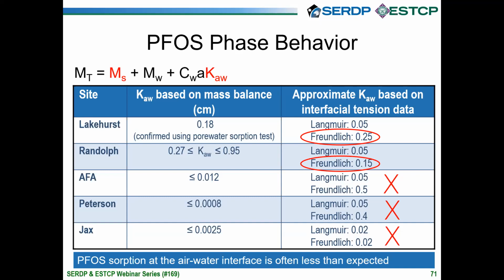So what can we say about these terms based on what we've measured? For the Lakehurst site, we did a lot of work there, and because we had so many lysimeters and a nice vacuum manifold system, we were able to collect a lot of pore water and do some air-water interfacial adsorption tests. So we have a pretty good estimate of what that KAW term is, with units of length, about 0.18 centimeters.